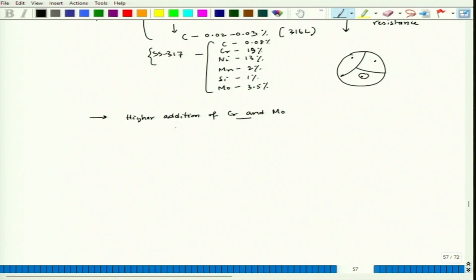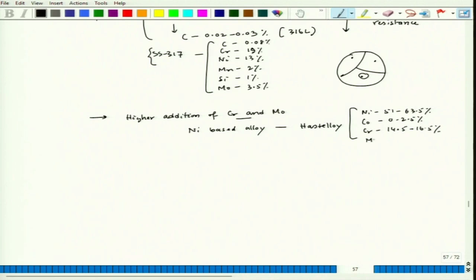So, some materials can be thought of, like nickel based alloys, sorry, not nickel based super alloys. So we can think of a nickel based alloy like Hastelloy. So, the typical composition: nickel 51 to 63.5%, cobalt 0 to 2.5%, chromium 14.5 to 16.5%, molybdenum around 15 to 17%.